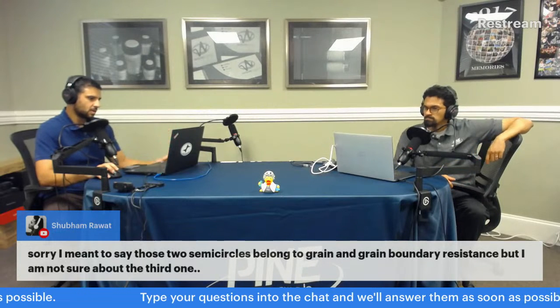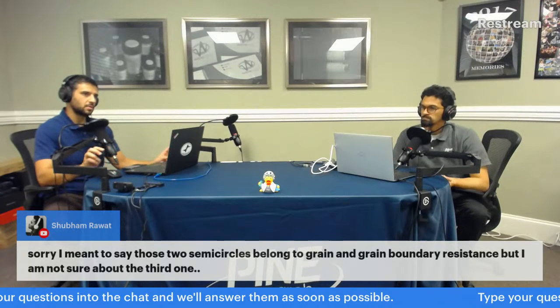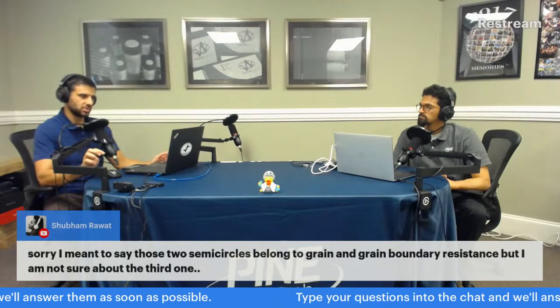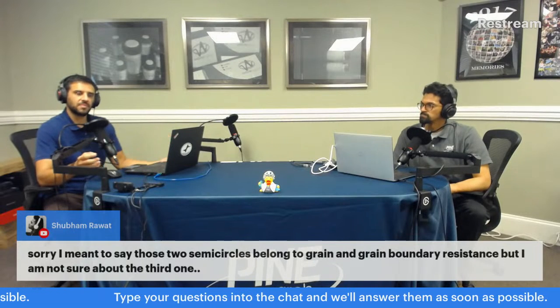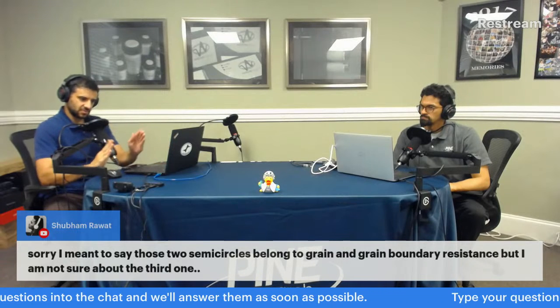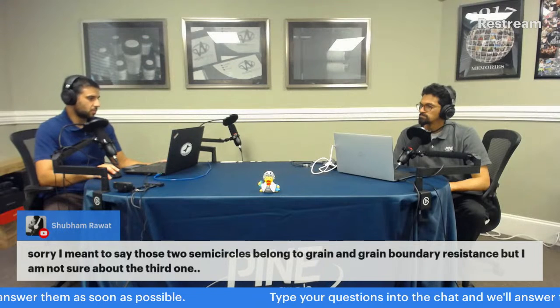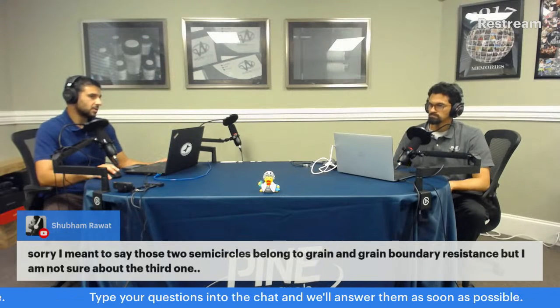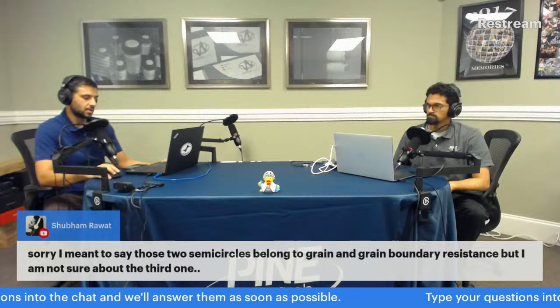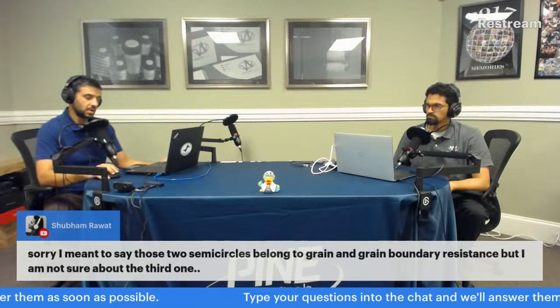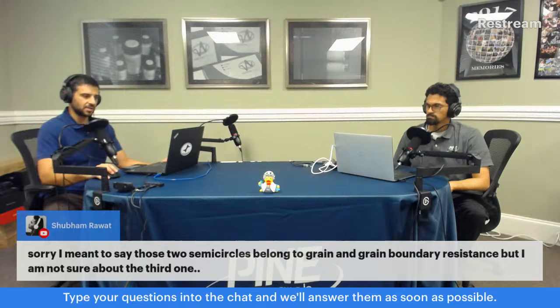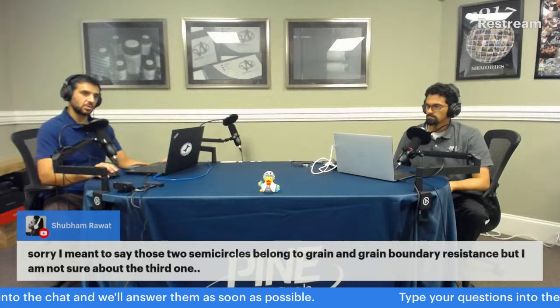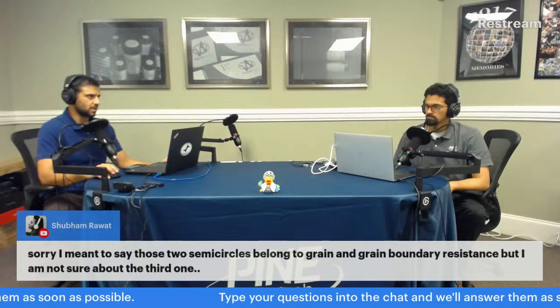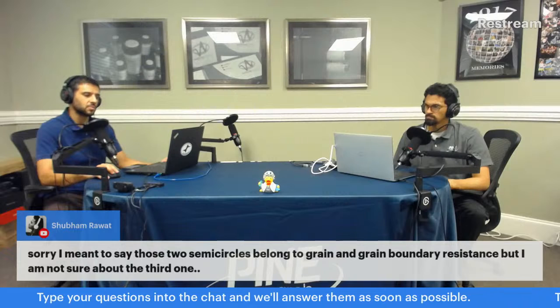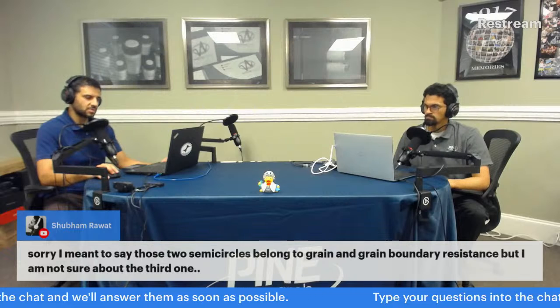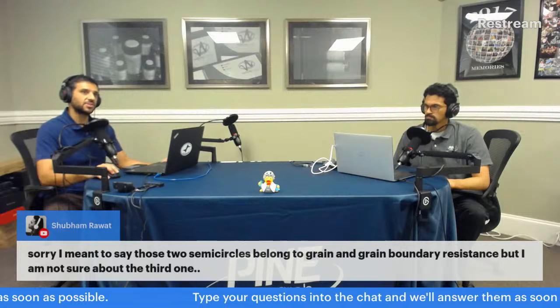So the third one, grain boundary resistance, is usually an in-electrode phenomenon. A grain boundary is between two parts of your electrode, which clearly has some layers or structure associated with the interface of two parts of something, and that's what's leading to that. Maybe the third one has to do with the electrolyte and electrode interface. Some oxidation or reduction process is occurring. There almost must be, unless your data is poor, and it might be the illusion of a semicircle, some sort of error. So do Kramers-Kronig on your data is one of my suggestions. Kramers-Kronig transforms, and that will see if it matches.